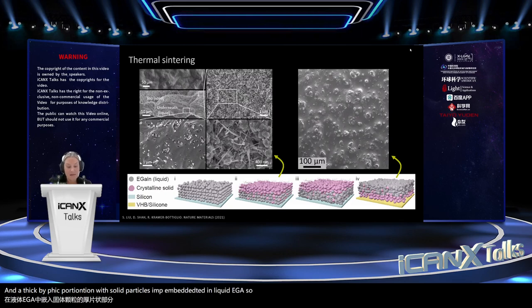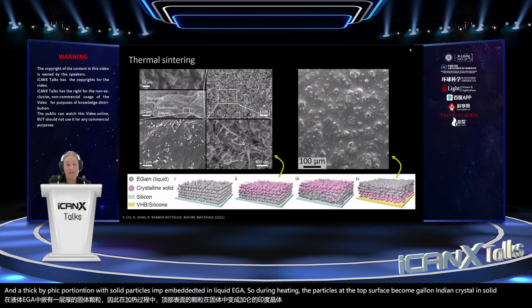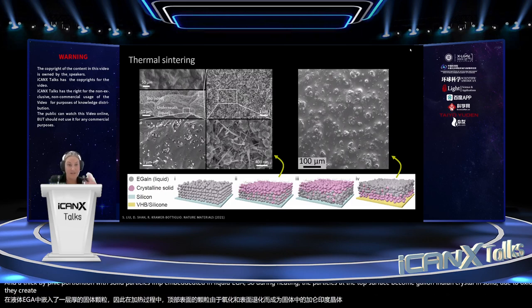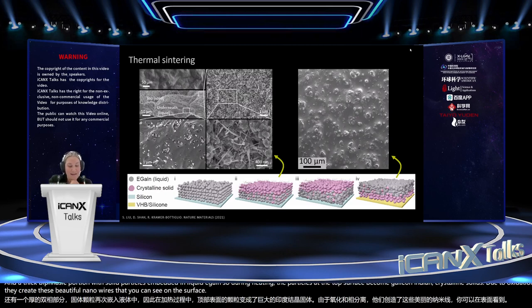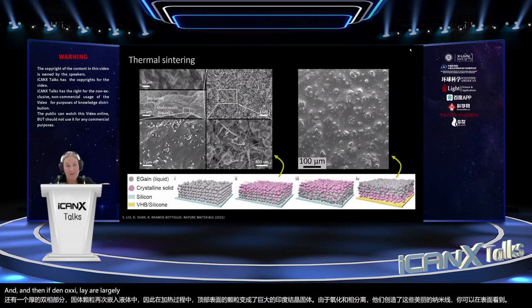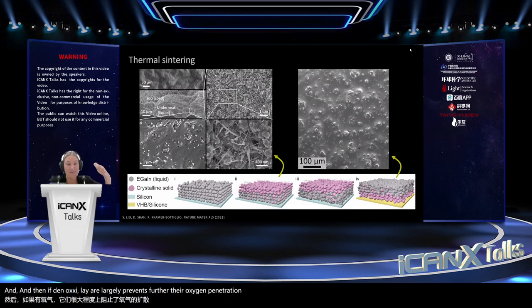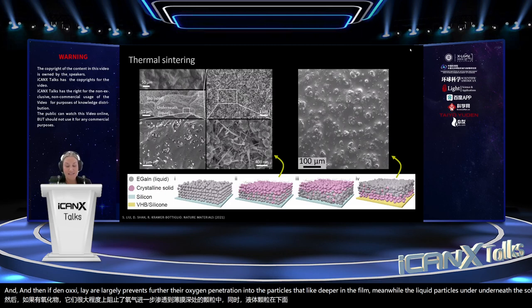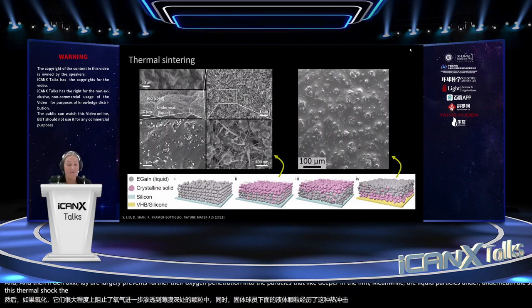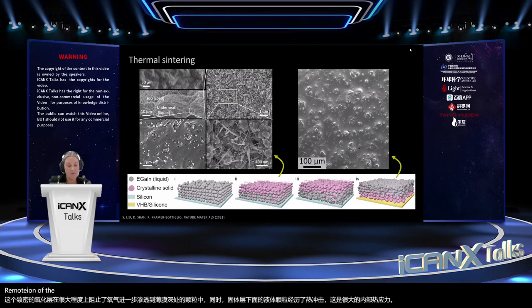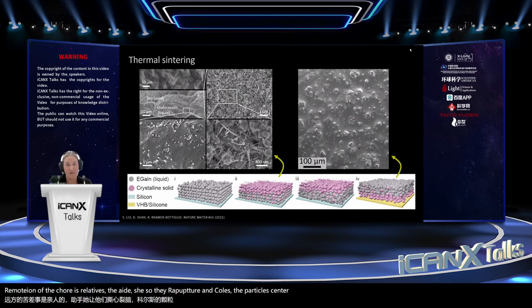So during heating, the particles at the top surface become gallium indium crystalline solids due to oxidation and phase segregation. They create these beautiful nanowires that you can see on the surface. And then this dense oxide layer largely prevents further oxygen penetration into the particles that lie deeper in the film. Meanwhile, the liquid particles underneath the solid layer experience thermal shock, significant internal thermal stresses owing to the larger thermal expansion of the liquid cores relative to the oxide shells. So they rupture and coalesce, sintering the particles below the film.